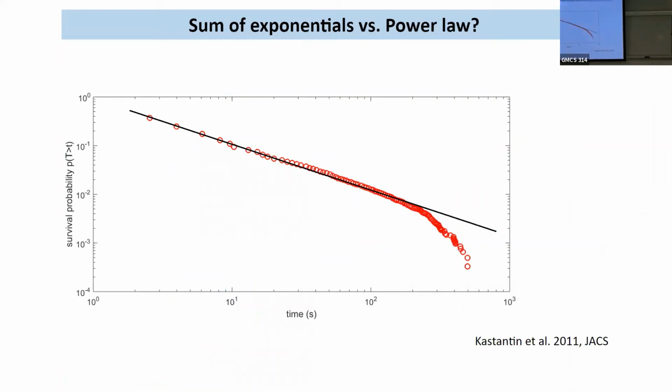And so then what we said was, okay, let's look at this. Instead of plotting on the log-linear scale, you plot it on the log-log, and you get this really strict linear regime, and then the last exponential one. And I was like, oh, look, this regime is actually power law. So the residence time distribution will be power law. Everything was power law at that point. This was 2017, and it was a big deal, like, oh, power law, you know? And so I was like, that's power law.